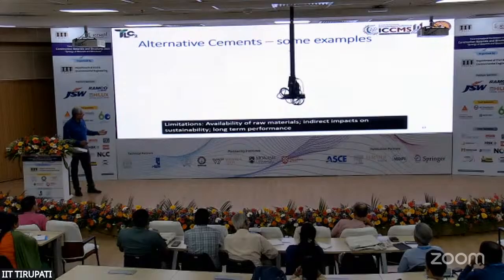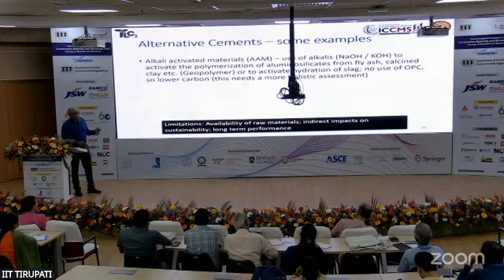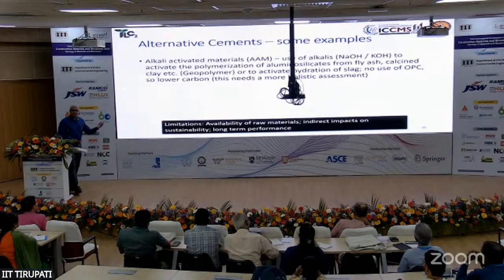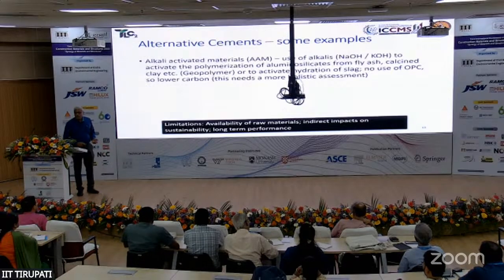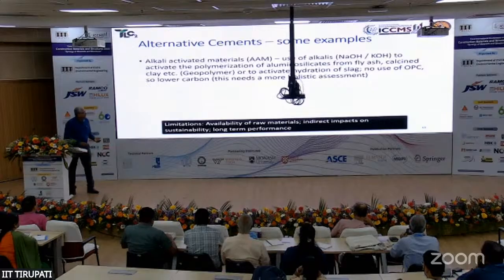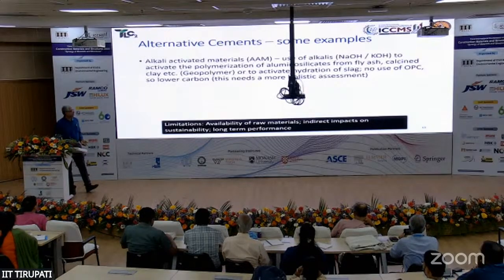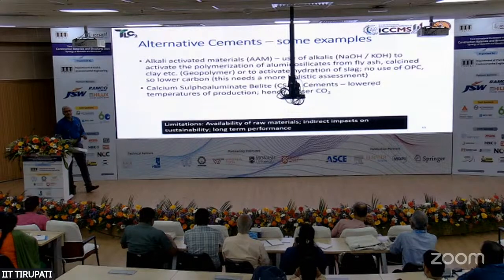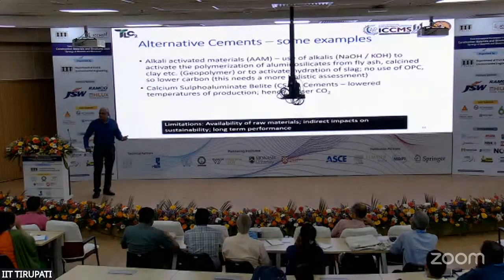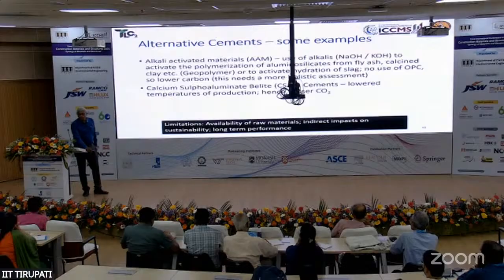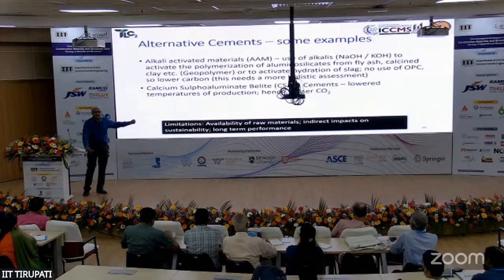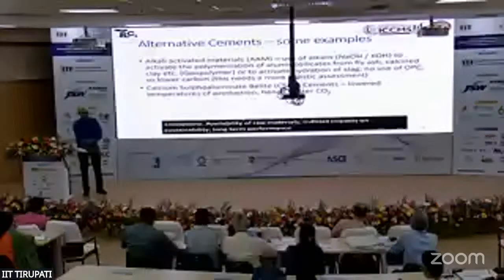Now, alternative cements, I said, you have, of course, alkali activated systems where alkalis like sodium potassium hydroxide are used to activate polymerization of aluminosilicate materials like fly ash or calcined clay, right? Or in case of slag, you do alkali activation of the hydration of slag. You produce slightly different systems with both of these approaches, but ultimately you're working in a system without any Portland cement. Now, calcium sulfoaluminate belite cements, again, in China, these are really big. The idea is that you produce cement at a lower temperature, right? With the right kind of approaches of selecting the right raw materials, and overall lower carbon dioxide emission happens in this process. The only problem here is the alumina sources that you need to look at are quite expensive, like bauxite, for instance. Even to produce calcium aluminate cement, the bauxite could be very expensive as compared to limestone.